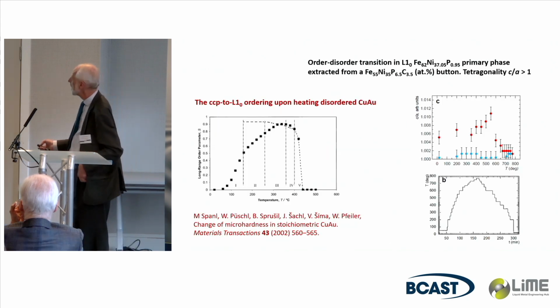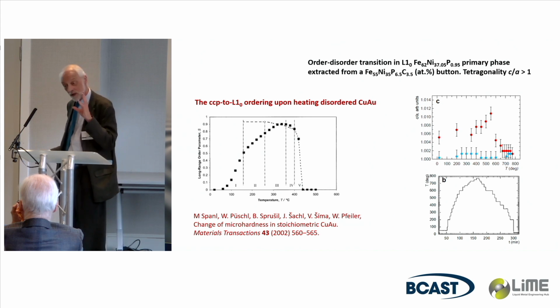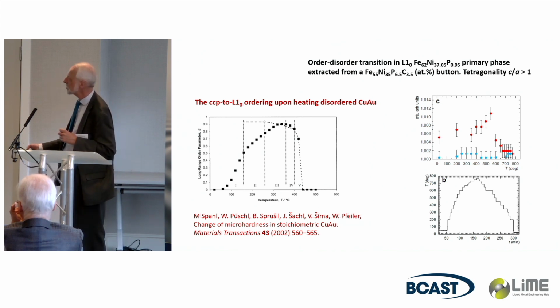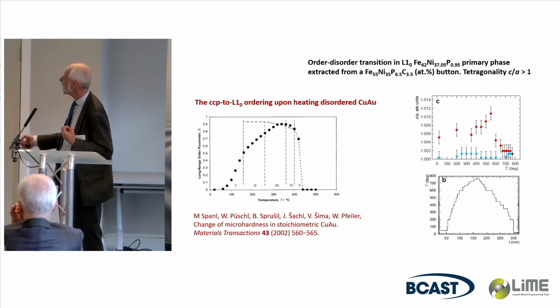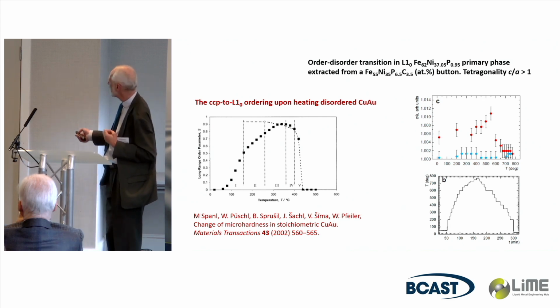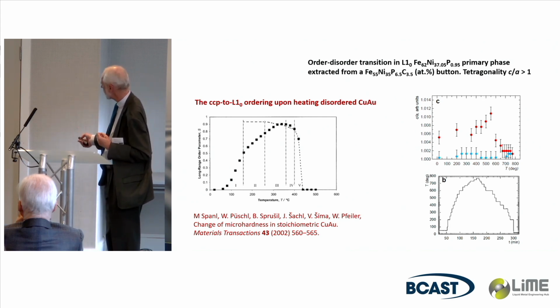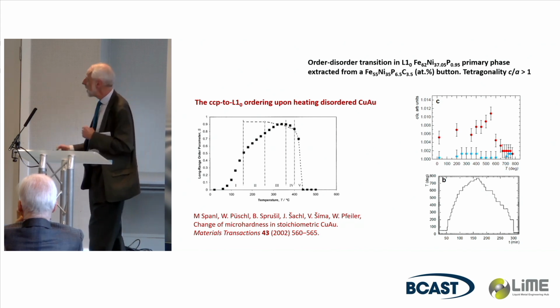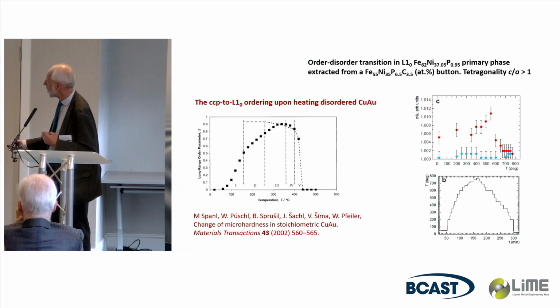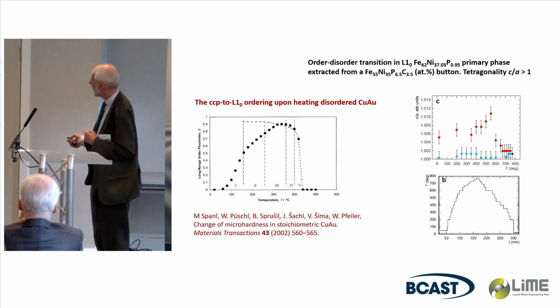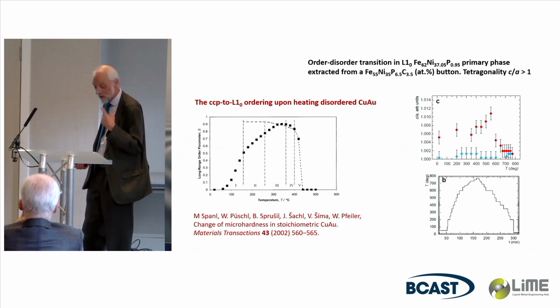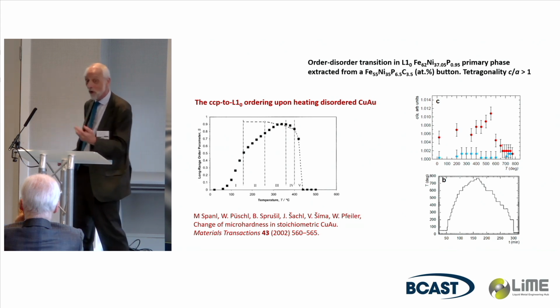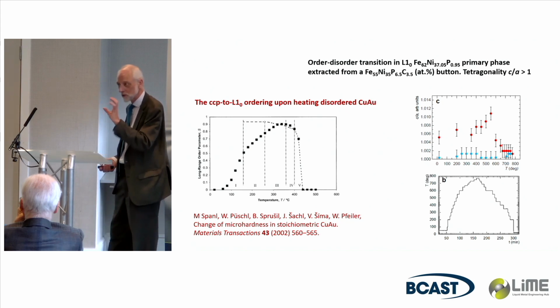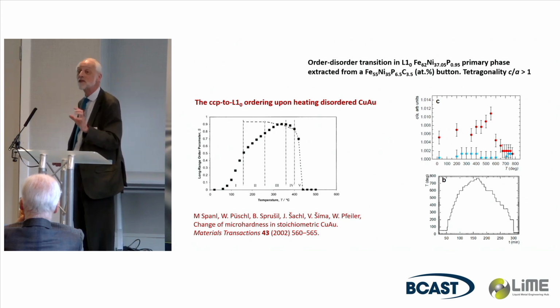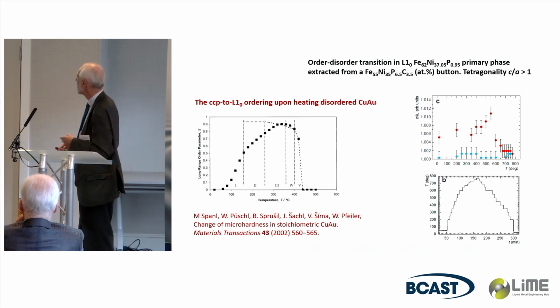This shows classic copper gold, which shows the same type of ordering in FCC, where you can quench it to be chemically disordered. On heating, it orders and then goes through the order-disorder transition. You see something similar with our tetrataenite, order crashing, and then when we cool, it does not reorder. It should reorder on cooling, and copper gold would, but nicely, in a way, that is just the same result as is found with actual meteorite samples, which also do not reorder on cooling. And there are various explanations, potentially, for why that might be so, to do with different ordering patterns developing.